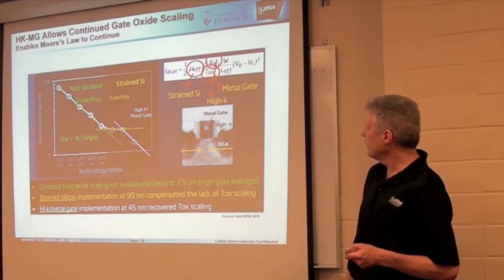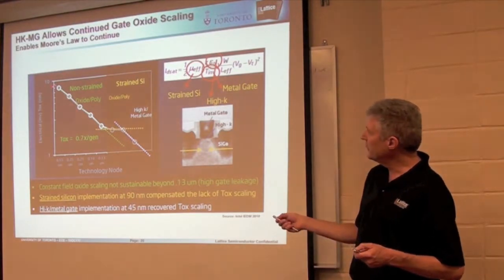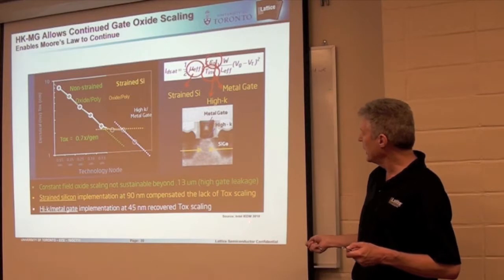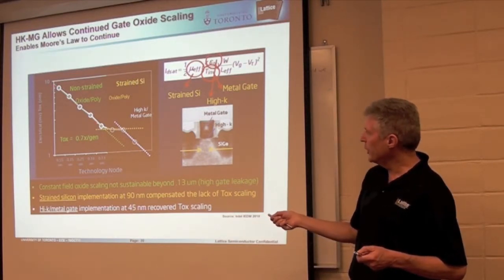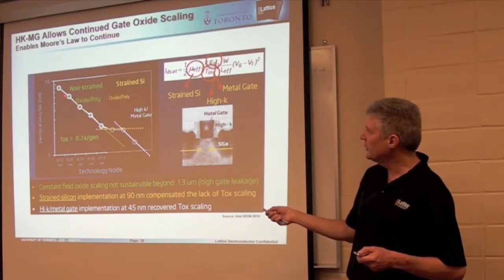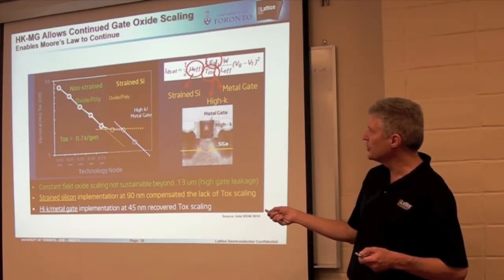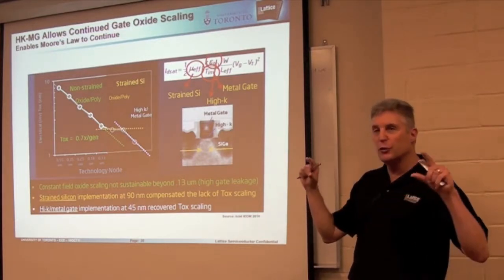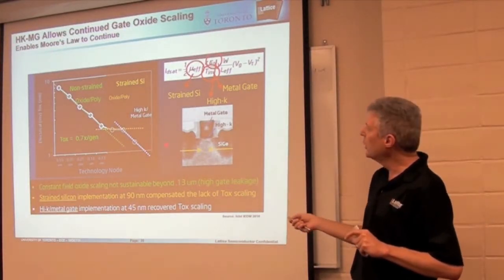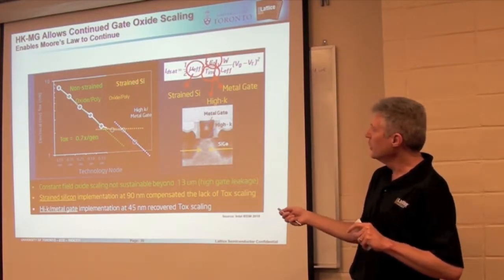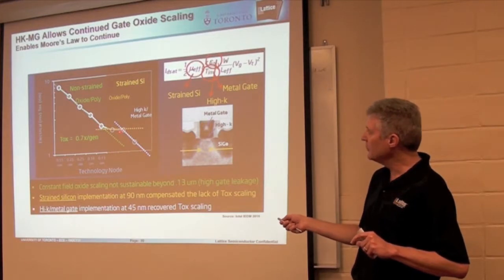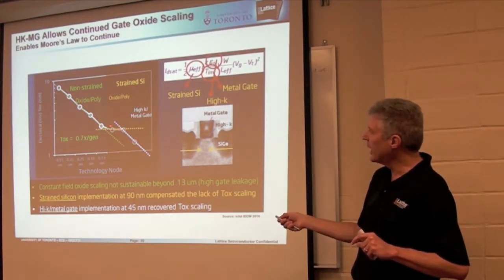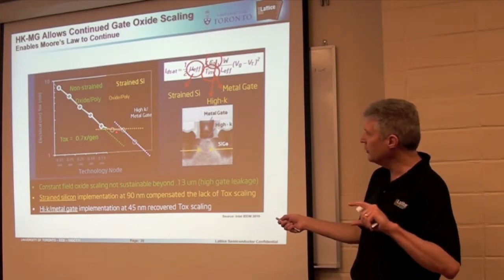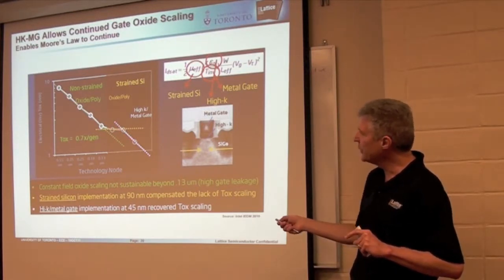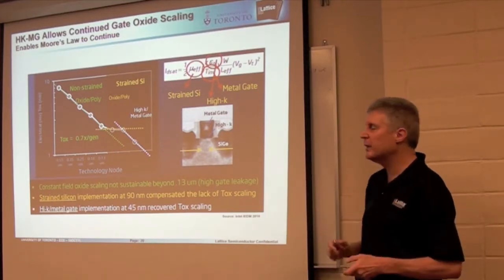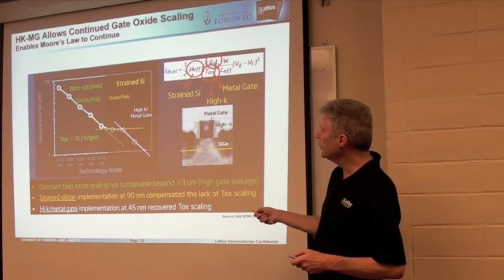Now, I won't spend a lot of time on this, but this is basically an Intel IEDM presentation where they're showing the same thing. This is gate oxide scaling, and gate oxide scaled by a factor of 0.7x for every generation up until 130 nanometers, after which we could no longer make the oxide thinner because it would punch through. So we resorted to things called strained silicon, which I won't go into, but that helped buy some time, and the HighK metal gate, but it didn't allow us to scale the oxide. HighK metal gate now allows us to pick up on oxide scaling again and continue to go down from there. So it just allows us to continue the trend that we've historically had.